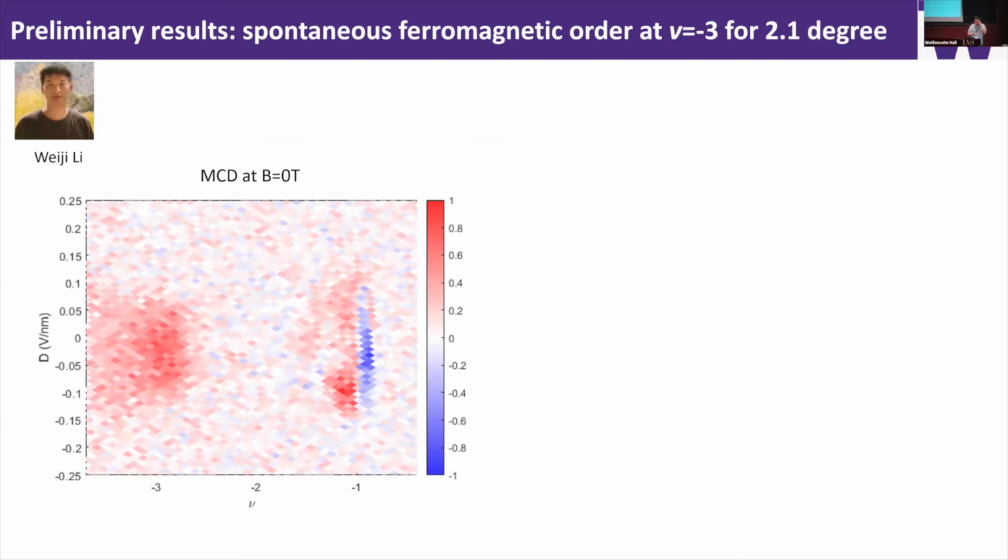So here are the results we have. The measurements were done by my postdoc Weiji. I'm going to just show you the main results from these 2.1 degrees. And again, hopefully at this point you are familiar with these MCD measurements, so I'm not going into details again. You can clearly see there's a non-vanishing MCD signal near the filling factor -3. And there is also MCD signal at filling factor -1.